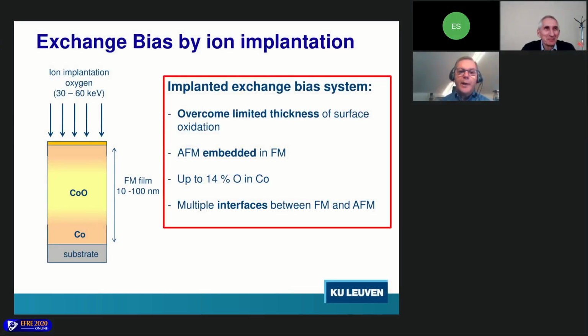So what we have been trying to do is to take an entirely different approach. First, we have grown a thick cobalt layer with molecular beam epitaxy, and then we put a gold layer on the top so that there will be no surface oxidation of our cobalt layer. And then we have taken this sample, and we have implanted ions of oxygen with an energy between 30 and 60 kiloelectron volt. And so what's happening then is that in the ion implantation process, you actually get a more or less Gaussian profile of implanted oxygen throughout the thickness of the film. Initially, we have used implantation conditions so that you get up to about 14% of oxygen in cobalt.